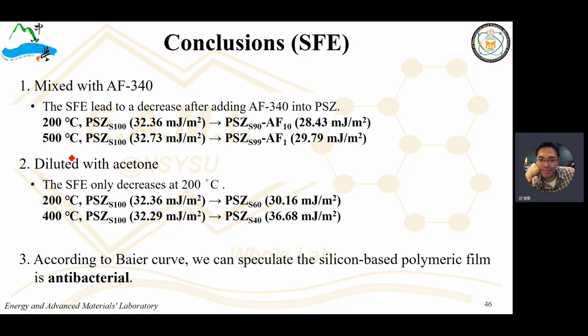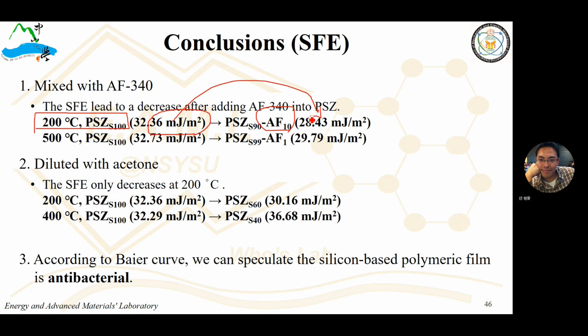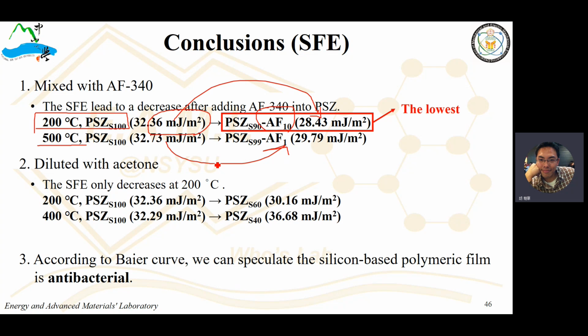For the pure precursor heated at 200 Celsius, its surface free energy is about 32. When we add about 10% of this fluorinated resin, its surface energy drops to 28. Even when this precursor is heated at 500 Celsius, the surface energy still drops. For the precursor diluted with acetone, we find the lowest surface energy is at about 60% of the pre-ceramic precursor. However, it's still higher than 30.